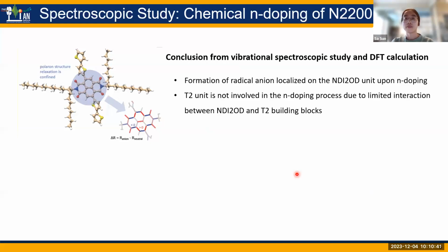So from their vibrational spectroscopy study and also the DFT calculation, they believe the polaron formed by the chemical doping is actually in the state of radical anion localized on the NDI unit of N2200. And the T2 unit is not involved in the doping because the large torsional angle limits the interaction.